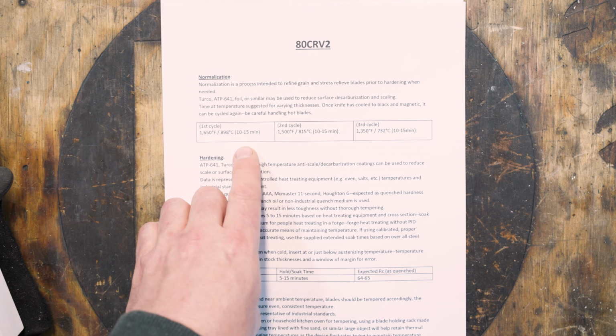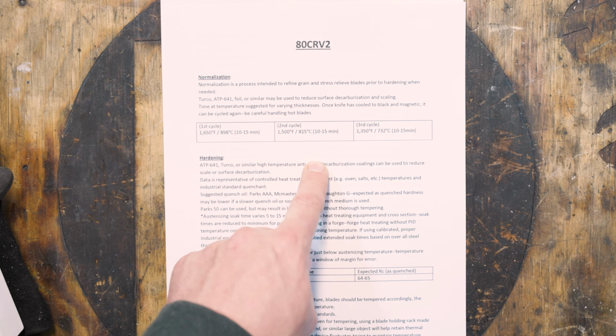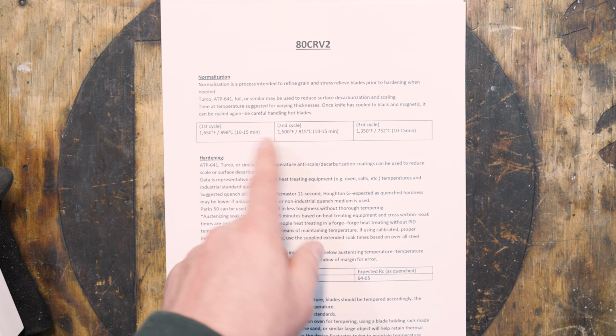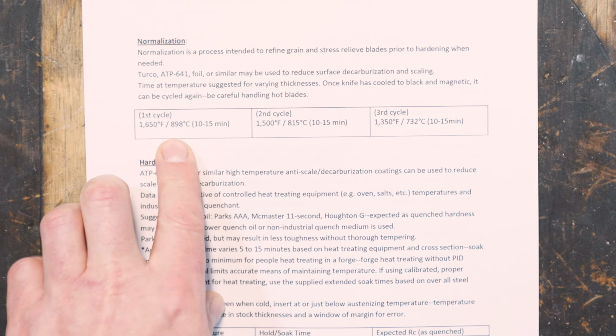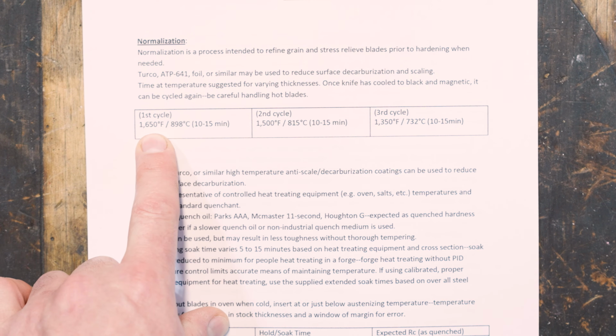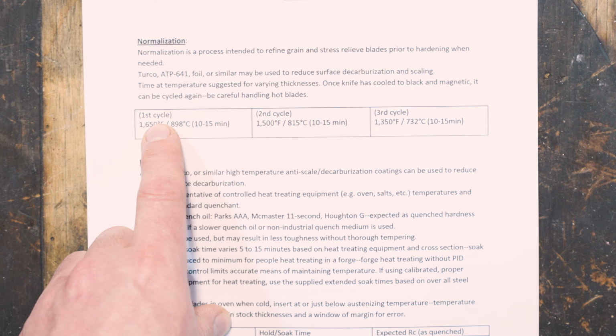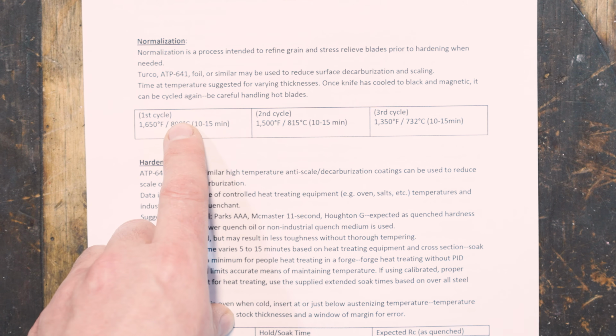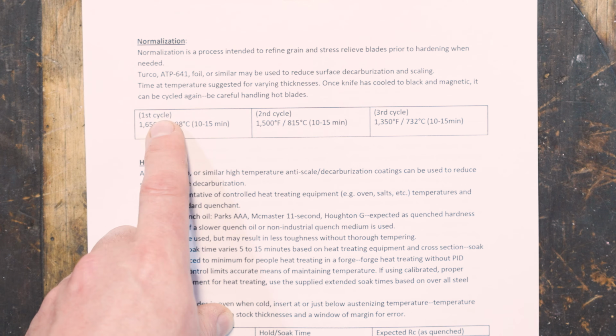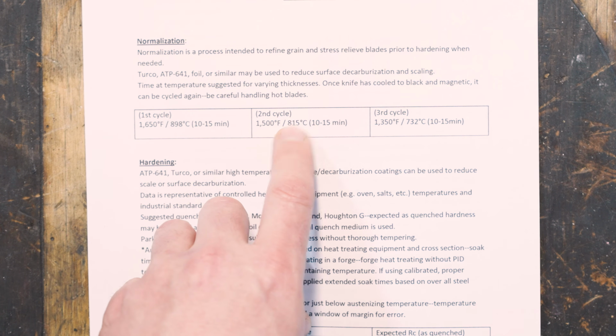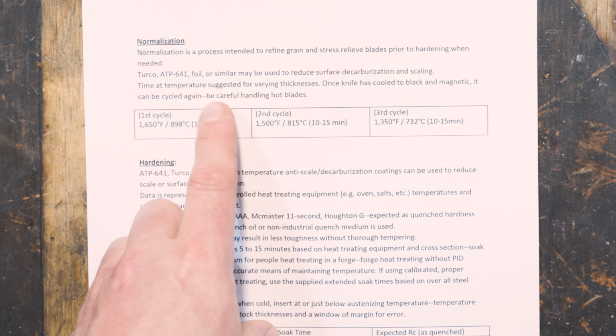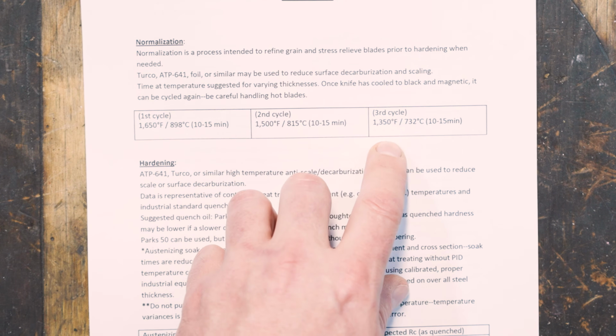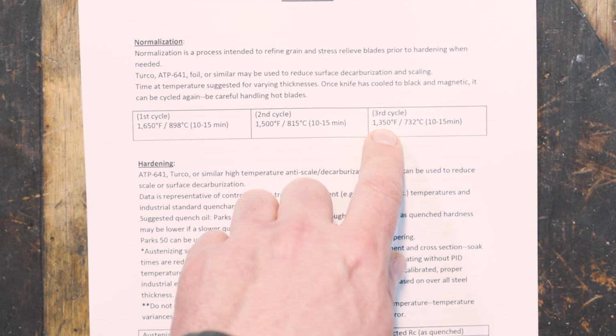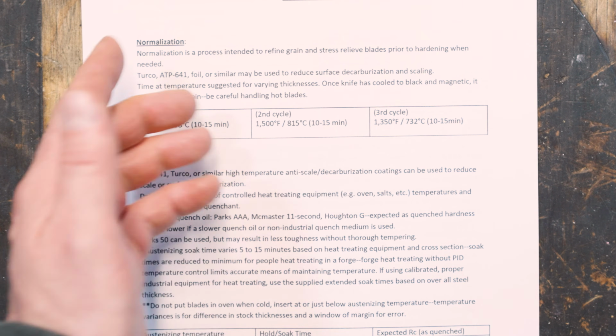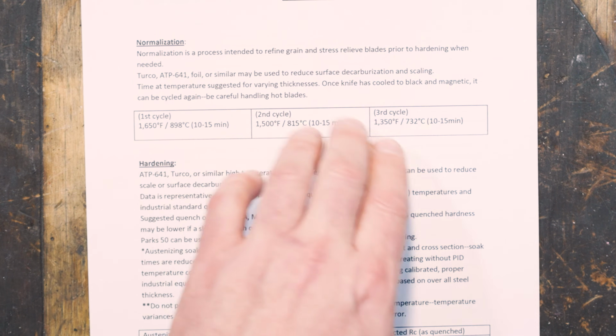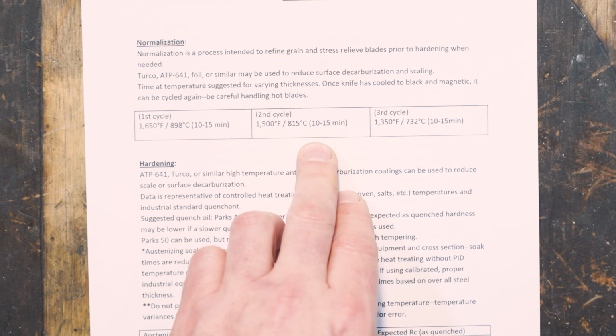And we are going to do a normalization cycle because this has gone through a whole bunch of transformation. The 80CrV2 not so much, but we're still going to normalize it. So to normalize, we're going to heat this thing up to 1650 degrees, and then we're going to pull it from the kiln and let it cool down to black. Once it's cooled down to black, we're going to put it back in at 1500 degrees. And then once it's hit 1500 degrees, we're going to pull it out and let it cool to black again. And then the third cycle is we're going to heat it up to 1350. And then once it's hit 1350, we're going to pull it out and let it go to black. That kind of resets the grain structure and makes it more manageable steel.